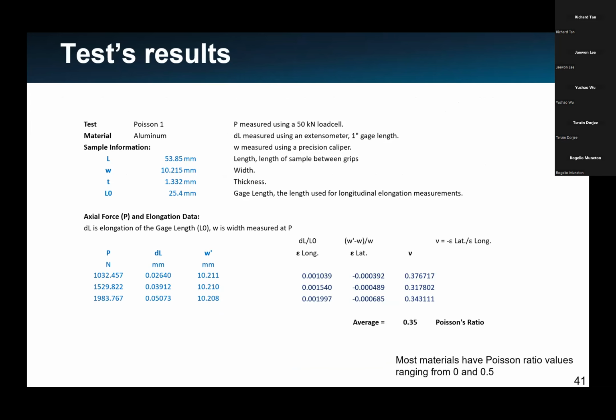In this test, we got the results and calculated the average Poisson's ratio for all three, and we got the average Poisson's ratio as 0.35. This sits well with the knowledge that most materials have Poisson's ratio values ranging from 0 to 0.5. And that's about it, thank you very much.